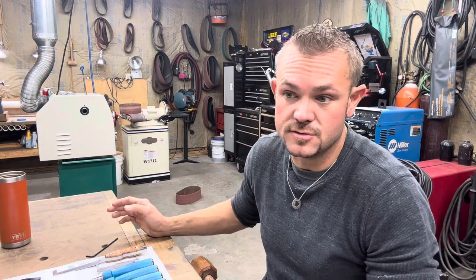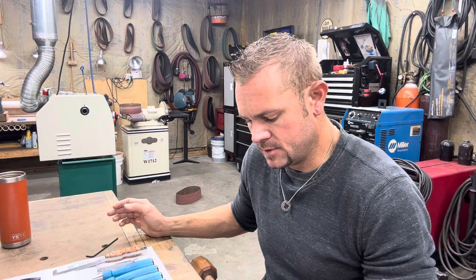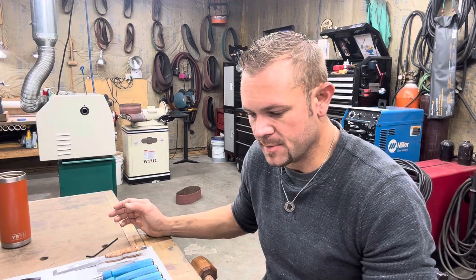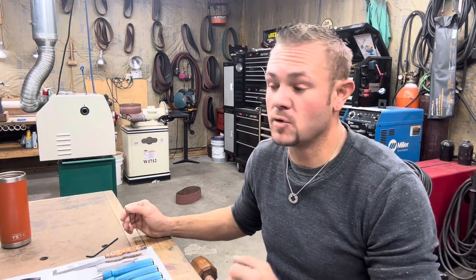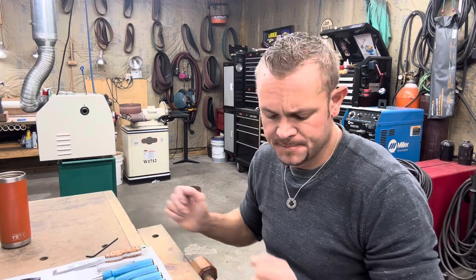Generally speaking, I hate to generalize because generalization doesn't work with metallurgy, but to put it in the most simple terms possible for people, the higher the temperature and the more rapid the quench, the less retained austenite you're going to have. But if that were true, you just heat the crap out of it and quench it in water, right? No, it'll crack, or you'll end up with a blade that has no toughness. Yeah, you're going to get a lot of hardness out of it, but what good is hardness if you cut a piece of pine and your edge cracks? That's too much heat, too rapid of a quench.